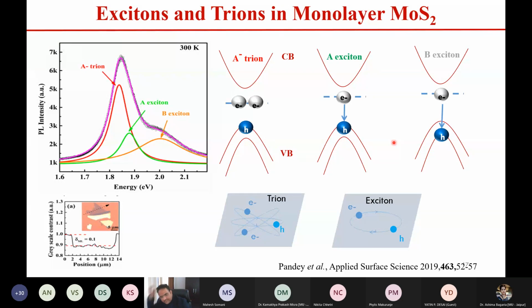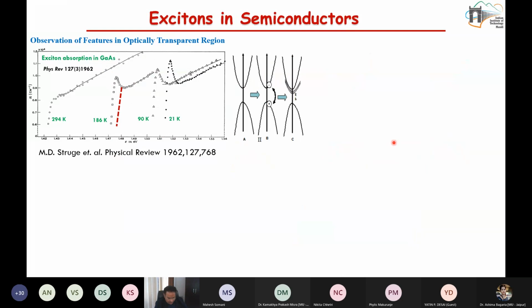But you know that this is a very interesting aspect, that you have one electron and one hole, okay, one positive charge and one negative charge, and this is equivalent to your hydrogen atom, yes. But before I go over the analogy with the hydrogen atom, what we can see is, if you cool down, so this is the optical absorption of gallium arsenide as a function of the energy. And what you see here is the room temperature data, okay. So it falls down, and from the slope of this graph you estimate the band gap of the material, okay. But if you cool down these materials, what you see is that there are some features appearing in the optically transparent region of these materials, and from where are these features coming?